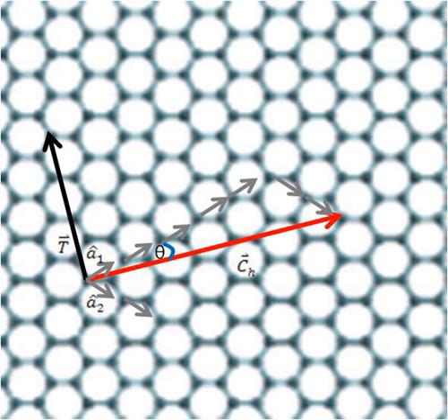For the semiconducting carbon nanotubes, there is a diameter dependency on bandgap. For example, according to a single particle tight binding description of the electronic structure, E_G equals gamma times 2a over d_t, where gamma is the hopping matrix element, and a is the carbon-carbon bond distance.